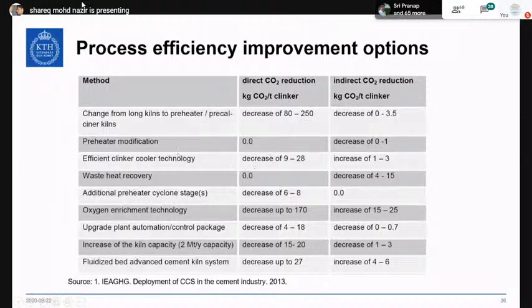Whereas you see all the other options, preheater modification, not much change of CO2 reductions, efficient clinker cooler technologies, very less, 9 to 28 kgs of CO2, which is again very less compared to the target that we have, around 700 to 800 kgs. The additional preheater, 6 to 8. Oxygen enrichment technology, we could decrease up to 170. So this is a major impact. But again, this will require changes in the equipment because it has to withstand the oxygen enriched air. Whereas the other options, still very less, 15 to 20, 27.